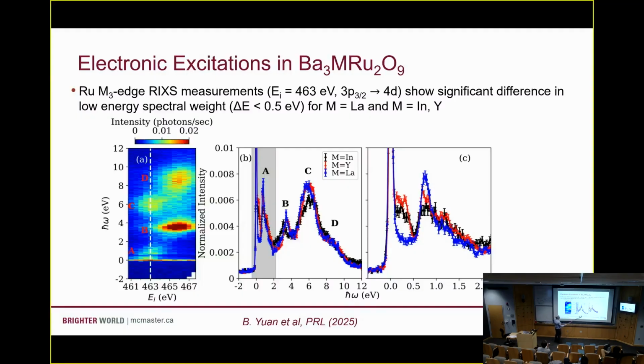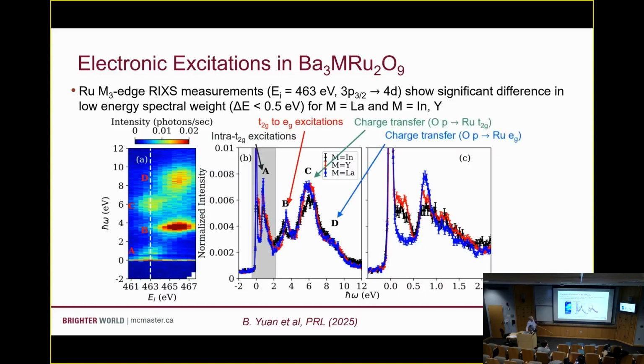Okay? So, as you might expect for materials that are structurally similar, a lot of the high energy stuff looks the same in all of these materials, right? So you've got peaks B, C, D here that look quite similar regardless of which of these that we're measuring. But if we focus on the low energy excitations here, so the stuff that's going on below half an electron volt, there's this really stark difference between the indium and yttrium compounds and the lanthanum. Okay? So we've got all of the spectral weight here that seems to disappear when we go from yttrium and indium to lanthanum, and the extra spectral weight that we pick up there. So again, just to label these nicely, intra-T2G, T2G to EG, and our 2 charge transfer excitations.